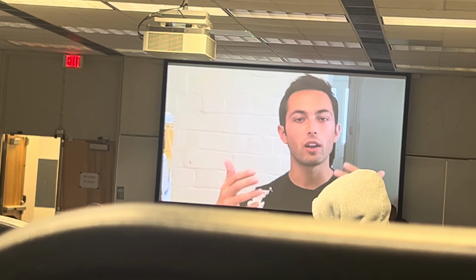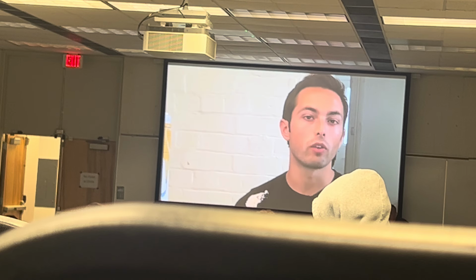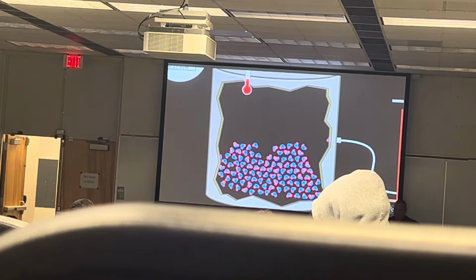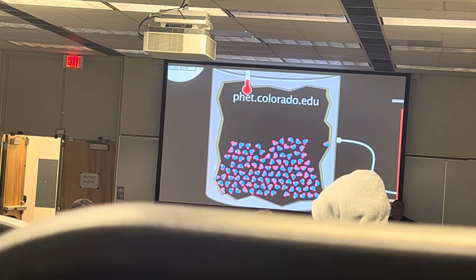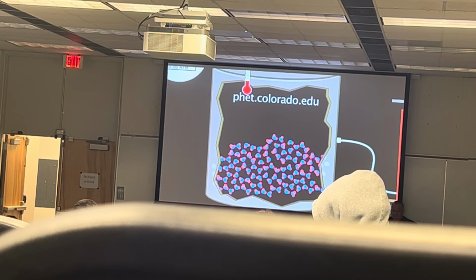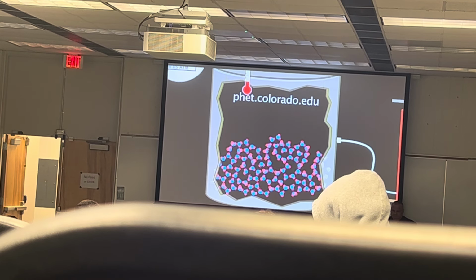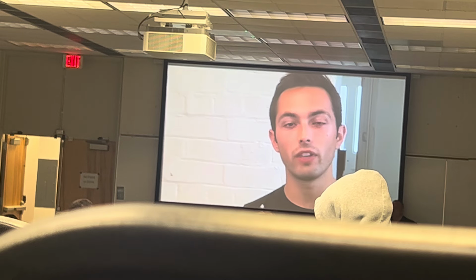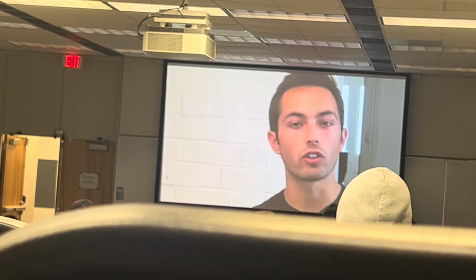So we're taking it below its temperature, below 0 degrees, where it should become ice. But it's very difficult for that water to make the transition without somewhere for that ice crystal to start growing. So what we need is some kind of nucleation event. If the water is not pure, the impurities in the water naturally act as sites where the crystal can start forming.